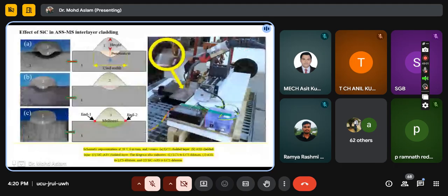After that, in the final conclusion, we observe that when we are using mild steel on the mild steel, the dilution will be more. That is okay. But in the cladding portion, the dilution will be minimum, so less metallurgical bonding formation occurs. So improving things like wear resistance, corrosion resistance, as well as hardness, we used stainless steel and developed it. Now in the second case, at the same parameters, we observe that dilution decreases as compared to mild steel. But here also we have observed incomplete fusion away from the center of the melt pool.